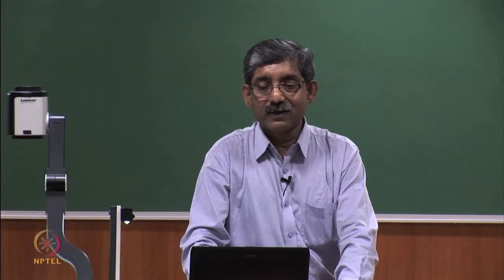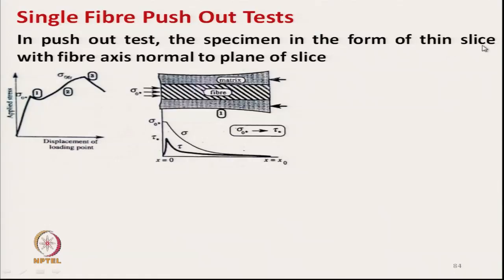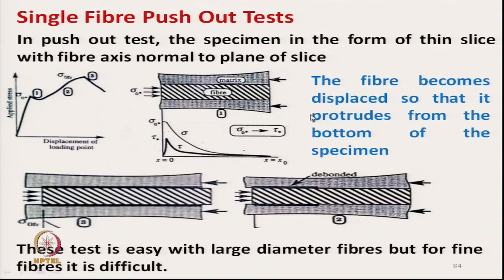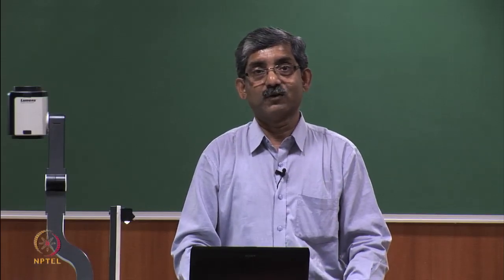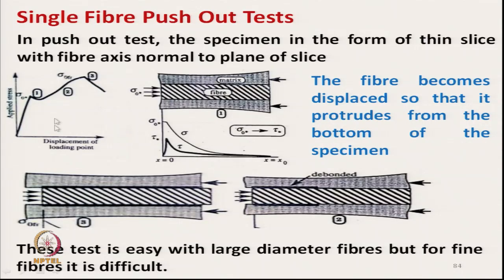That is, in the push out test the specimen is in the form of a thin slice with the fiber axis normal to the plane of the slice. So, this is the plane here, and this is a single fiber, and this is the slice thickness, and the fiber is being pushed out of this place. The fiber becomes displaced so that it protrudes from the bottom of the specimen, from the other side it will come out. This test is easy with large diameter fibers, but for fine fibers it is difficult. The thickness of the fiber should be sufficient, otherwise it is very difficult to push out. So, this shows again debonding, propagation and frictional sliding.